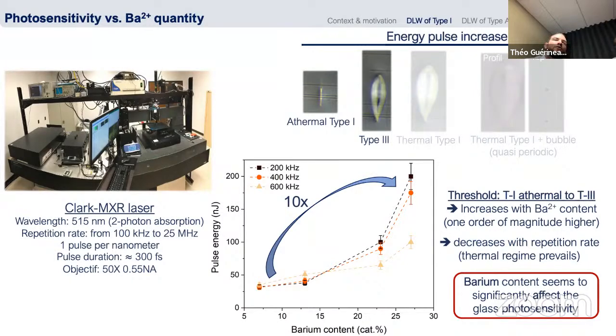What is kind of unusual is you go directly to the thermal type 1, and then to the type 3 when you increase the pulse energy. It's like the reservoir of type 3 is empty, and you favor only the thermal type 1, as if you could only make the type 3 disappear in contrast to the thermal type 1. I know that usually you go from type 1 to type 3, but in this case, I don't know if it's due to the wavelength that we used, but whatever the repetition rate, we observe the same evolution of the modification.